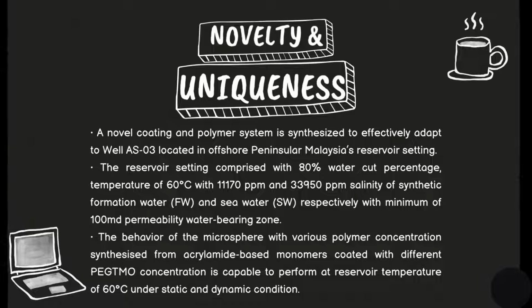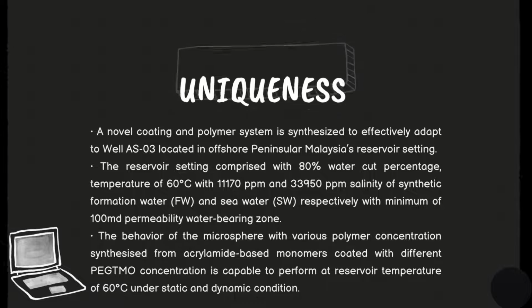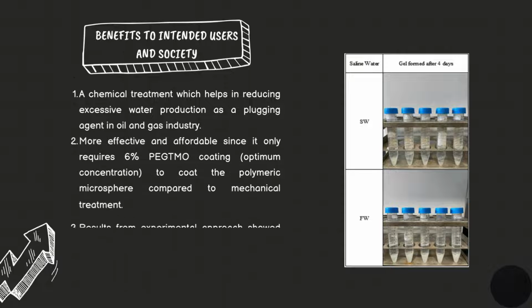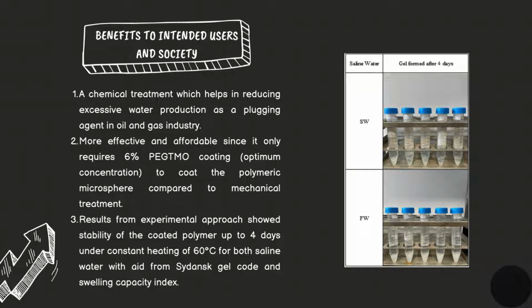The behavior of the microsphere with various polymer concentrations synthesized from acrylamide-based monomers coated with different PEGTMO concentrations is capable of performing at reservoir temperature of 60 Celsius under static and dynamic conditions. Next, the benefits to intended users and society. This project consists of a chemical treatment which helps in reducing excessive water production as a plugging agent in the oil and gas industry. Secondly, it is more effective and affordable since it only requires 6% PEGTMO coating, which is the optimum concentration to coat the polymeric microsphere, compared to mechanical treatment.